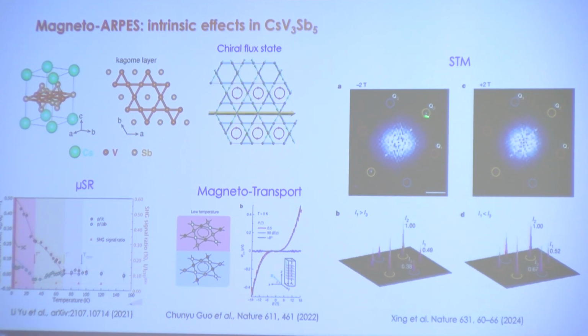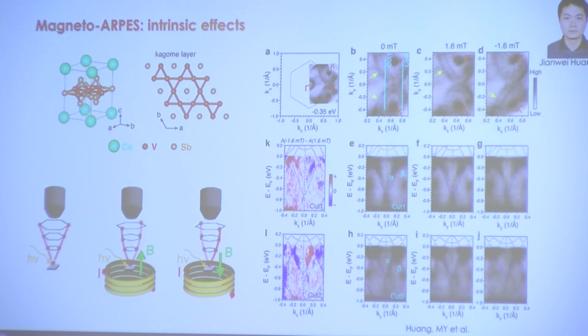But they see that the CDW peaks, as they get from the Fourier transform, have a chirality given by the height of these peaks, and that chirality changes depending on the sign of the magnetic field that you apply, right? So this seems like an ideal material that seems to be really responsive to tiny fields. So we put this to the test. I'm going to show you unpublished data.